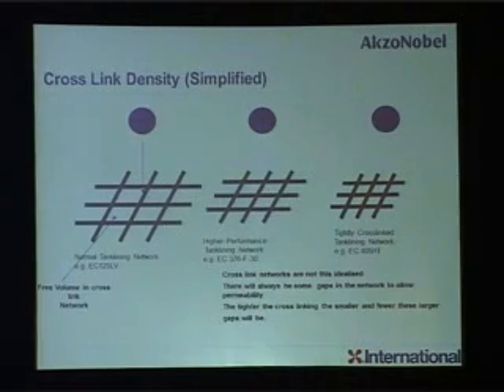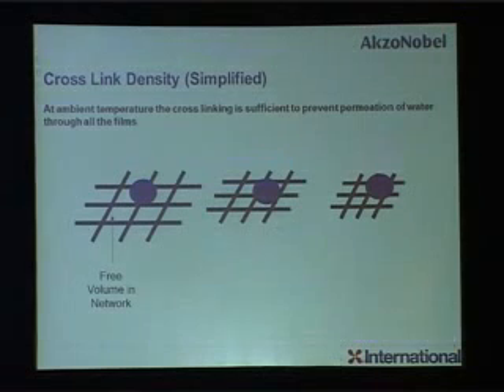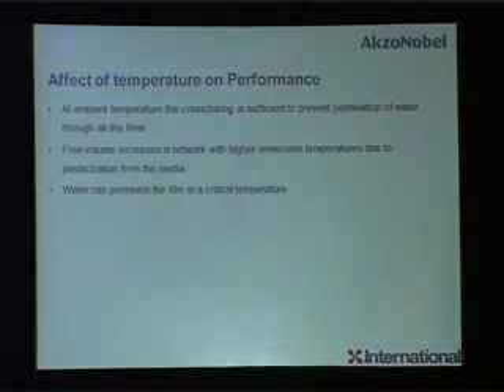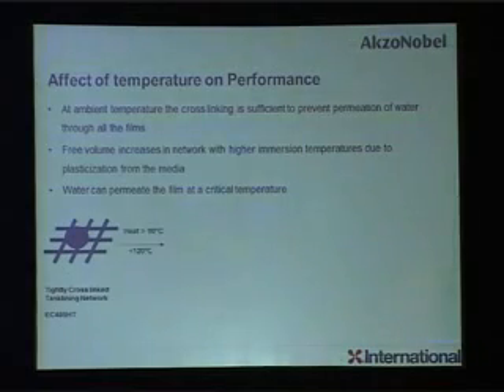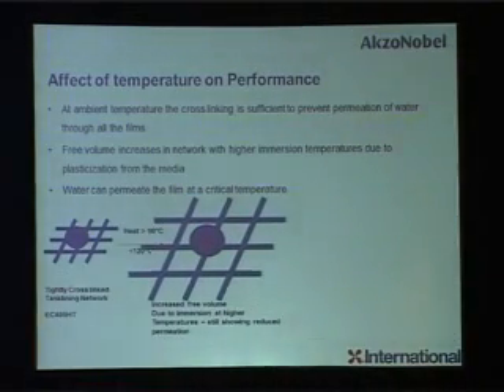So what I am trying to explain here is that how your coating film performs in resistance depends on your crosslink density. Now crosslink density comes from your epoxy molecules, the epoxy functionality. If this is not the case, your free volume is very high. So any water molecule or any molecule can go inside, and it will create a failure problem. So you should have a better and better crosslink network to get better chemical resistance and a better application environment. So for example, a coating which is very good at ambient temperature may not be good at high temperature, because at that time your coating will expand and it will have a very high free volume.